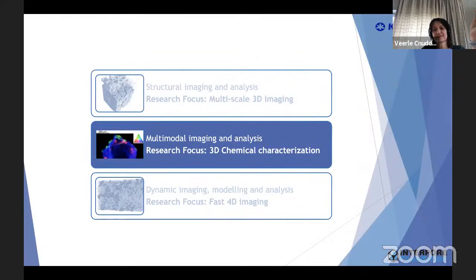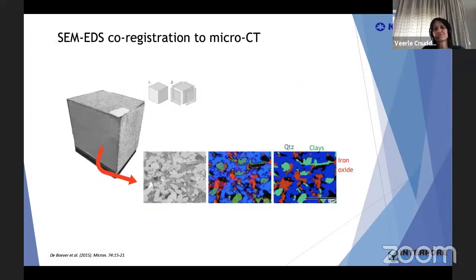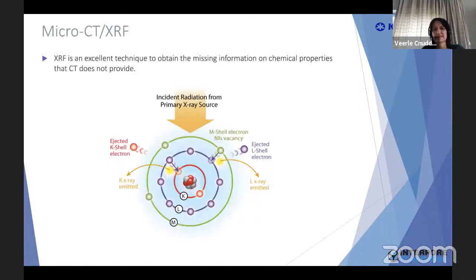Another important step is 3D chemical characterization. One approach is combining X-ray CT with scanning electron microscopy by registration. For instance, you have your rock already polished, you scan it with CT, you then put it under an SEM-EDS to get the mineral mapping, and then you combine the gray values on your surface with what you get from the SEM-EDS signal.